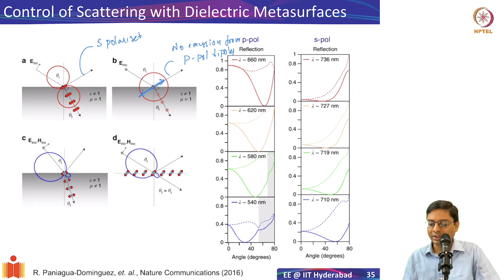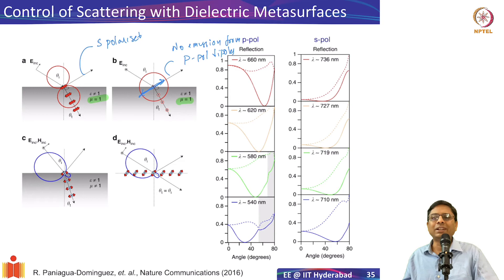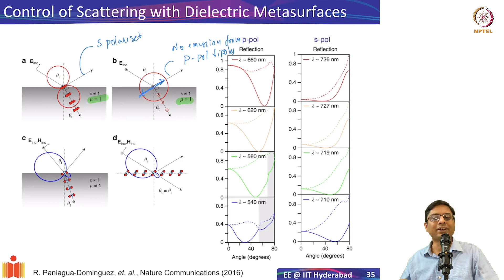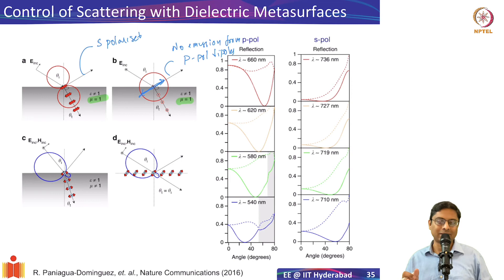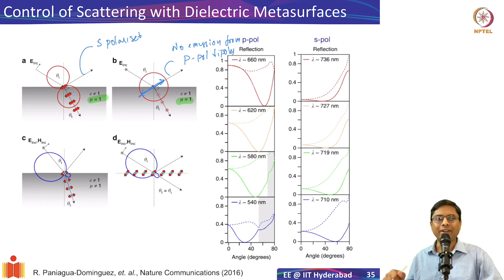Until not long ago, most people considered Brewster's angle a fixed material property: the arctangent of the refractive index. The conventional case has epsilon not equal to one but mu equal to one — no magnetic activity. But with metasurfaces, Brewster's angle is no longer a fixed material property. By exciting both electric and magnetic dipoles in a dielectric structure and carefully designing the resonances, geometry, and periodicity, you can engineer zero reflection for both s and p polarized light — the generalized Brewster effect, explained by Ramon Paniagua-Dominguez at A*STAR.